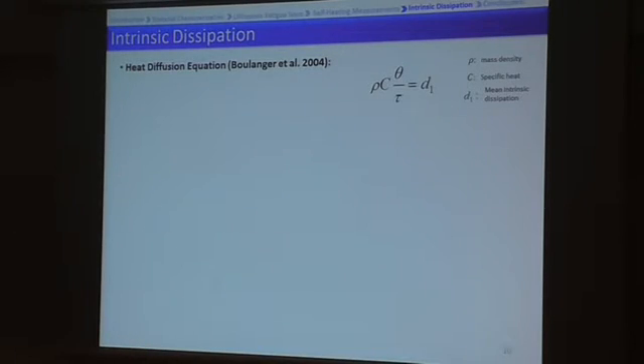Afterwards, we use the obtained diagram of theta F and the previous measurements for temperature evolution after stopping the test by using this simplified heat diffusion equation developed by Boulanger and his co-worker, as shown in this relationship. In order to measure the dissipated energy, the intrinsic dissipated energy shown by D1, here in this equation, rho is the mass density, C is the specific heat, theta is the temperature increase shown in the previous slide, and tau is a time constant which represents the thermal exchanges between the specimen and the environment.